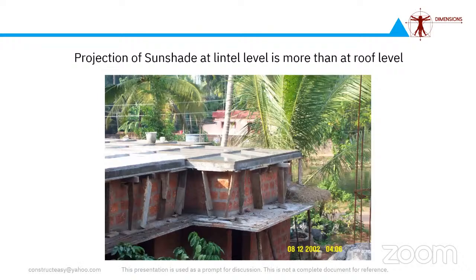If you can see this, almost all the buildings in the state of Kerala, they don't finish the roof slabs flush with the wall lines. They have a projection. If you can see this above the lintel, they have given additional supports in order to protrude or cantilever the roof slabs outside the plumb of the wall. This is a very good practice. This will avoid that horizontal crack, because whatever expansion happens in the slab happens in the free end, and therefore nobody notices a crack. If the slab needs to expand, it expands in the cantilever portion. If it has to contract, it contracts in the cantilever portion.